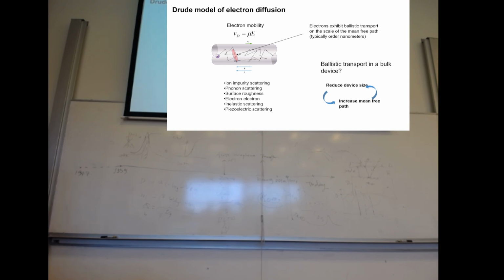Anyways, to have the graphene less scattered, we have two ways. One is to reduce the size of the system, to have the system smaller than the mean free path. Then electrons inside the system will not have any chance to scatter with anybody before they reach from the source to the drain. And the other way, of course, is to increase the mean free path. Increasing the mean free path seems to be harder compared to reducing the device size, right?